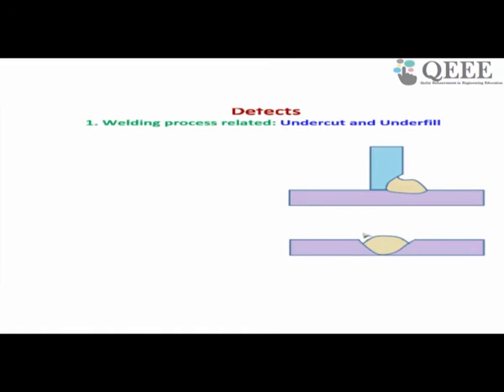Sometimes, if you want to join two pieces like this, this is a perfect joint. Similarly, this is lap welding, and if you want to join two pieces by butt welding, this is a perfect joint. But again, with high electric current and fast processing speed, you will have this kind of defect at the interface. It will not be able to melt and solidify at the corner region, because you get this kind of joint by multiple passes. This may be the last pass.